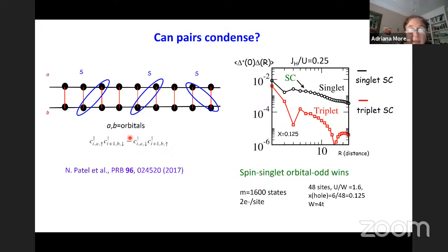We calculated the pairing correlation functions as a function of distance and found that the singlet decays more slowly than the triplet, and the rate of decay for the singlet is similar to the rate of decay for orders that are enhanced in one dimension. We think this could be evidence of a tendency toward pairing in multi-orbital Hubbard models, in regions where the relationship between U and J is right. It doesn't happen for all values of the parameters.